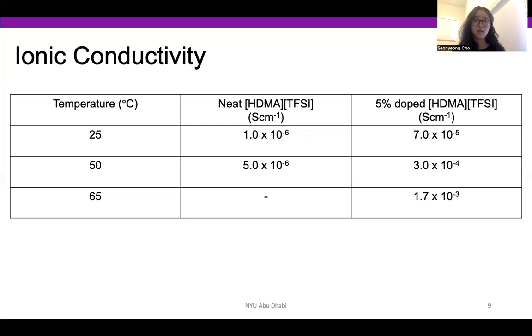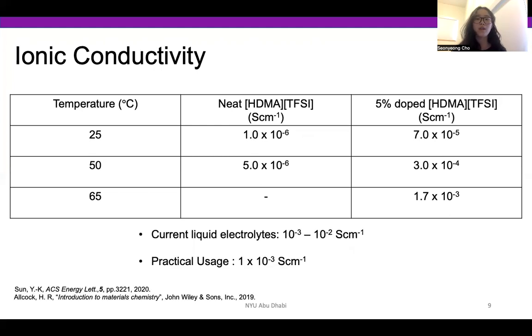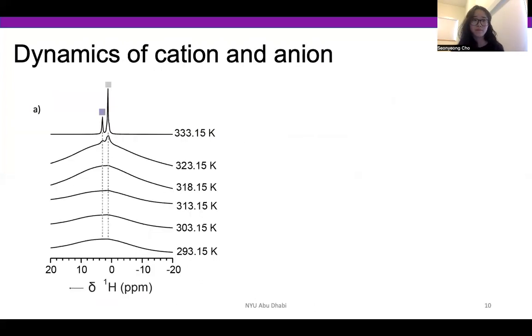to more ion conduction. And also these ionic conductivities show possibilities of incorporating this material as solid state electrolytes, because the current liquid electrolyte has ionic conductivities of 10 to the negative 3, 10 to the negative 2 Siemens per centimeter, and 10 to the negative 3 Siemens per centimeter is actually required for practical usage.